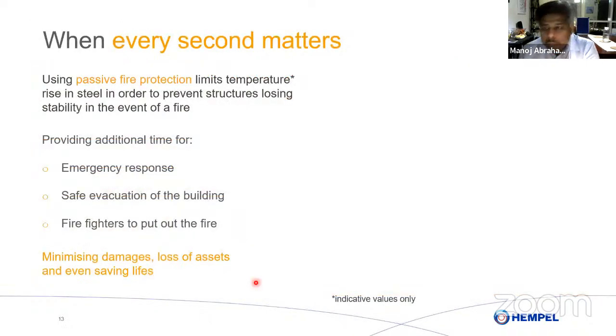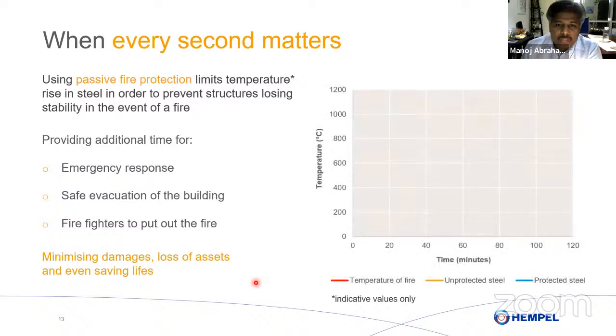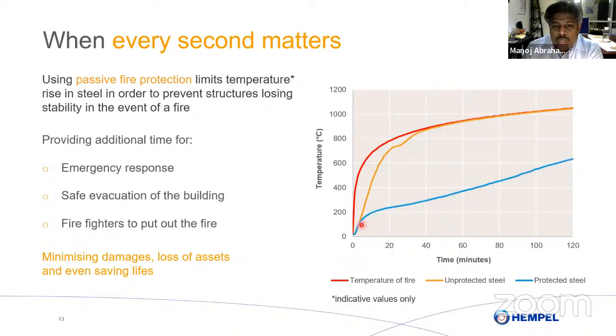So the whole idea behind fire protection is to give time, right? As I explained earlier, we want to ensure that we save lives and we are also trying to protect the asset. As we discussed, this is a cellulosic fire curve. Within 15 to 20 minutes, you can see that it has reached almost 800 degrees centigrade. The steel, if unprotected, will cross 700 degrees centigrade within 10 minutes. But if you protect it with an intumescent coating, we can ensure that it does not exceed 620 degrees centigrade. Steel at 620 degrees centigrade would still have about 40% of its load carrying capacity. Therefore, the structure will not collapse.